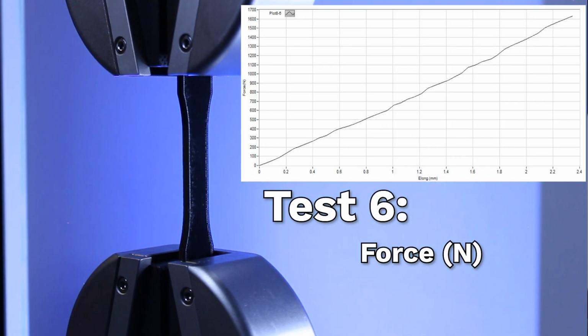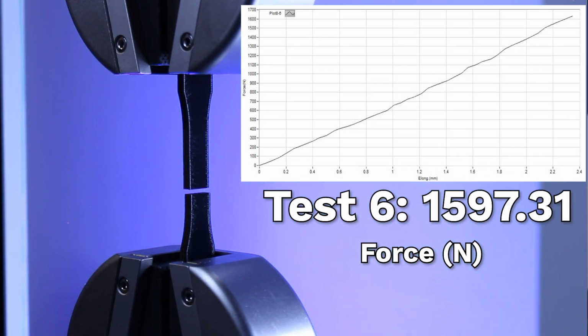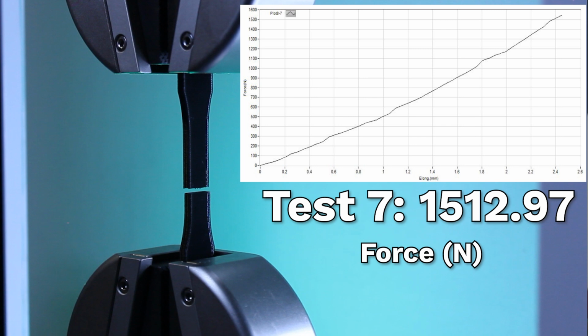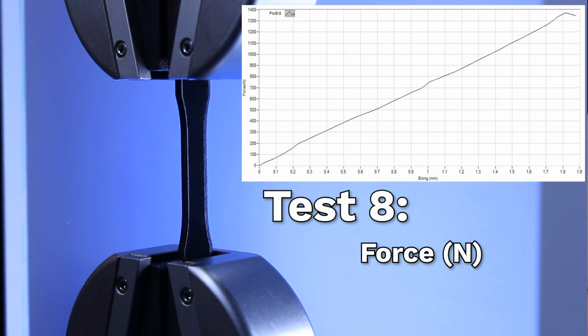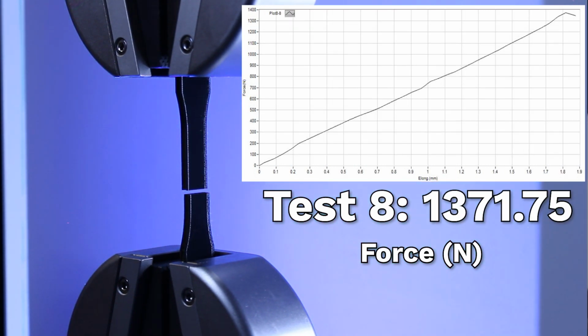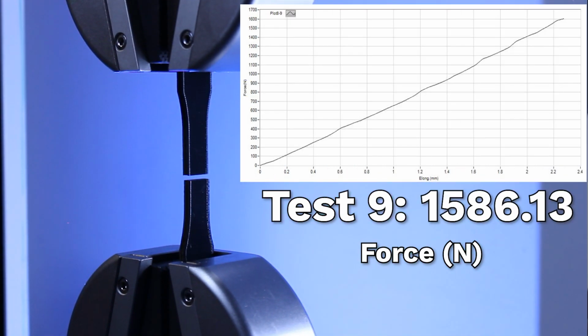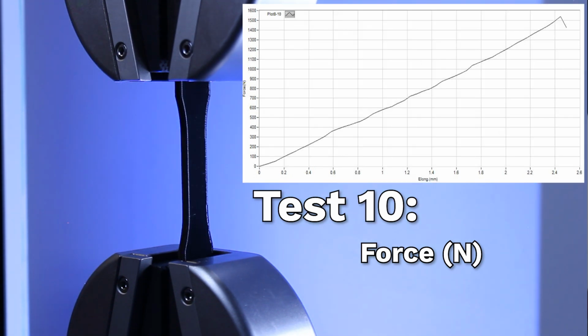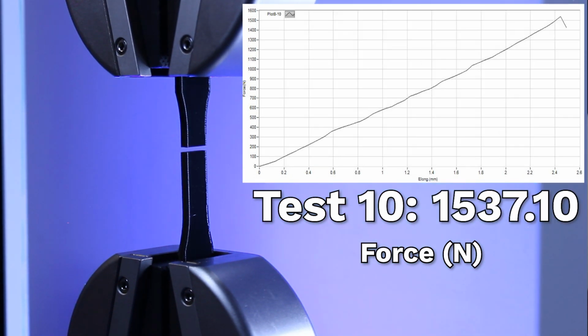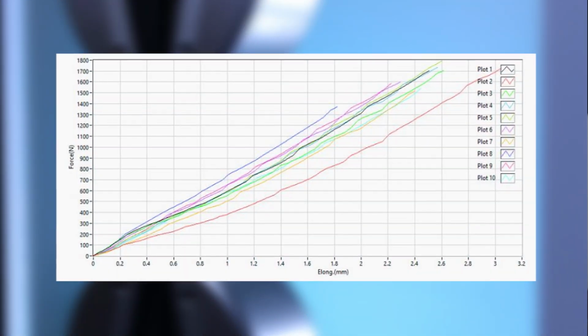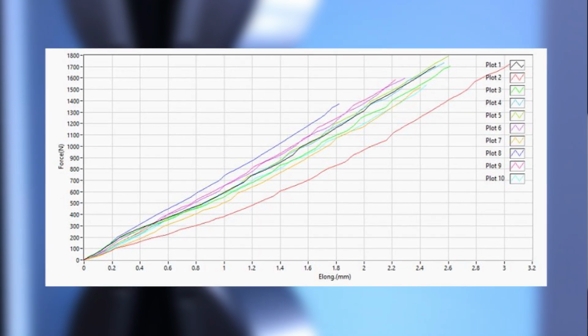That translates into about 30 to 32 megapascals of stress on these parts, which is about half of what was projected, which is what we would expect from past research. So at least now we're being accurate. And it was really good to see from these tests that all of them were in the same range, which indicated that the consistency of our test was pretty well there. Even though there's variability within 3D printing, it was not dramatic.